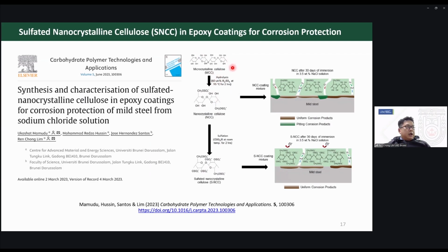We didn't start from a biomass feedstock here, because we wanted a more controlled study, so we used microcrystalline cellulose you can buy from Sigma Aldrich. Then we conducted some acid hydrolysis. We know that when you do acid hydrolysis, you don't just break the glycosidic bonds, you can also sometimes add on the first hydroxyl, and you can already start introducing sulfate groups.